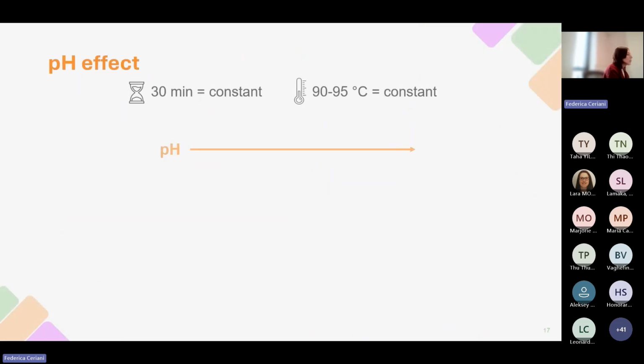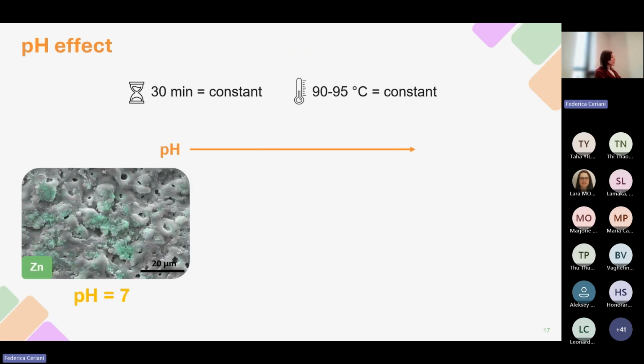To evaluate the pH effect on the sealing post-treatment, different tests are carried out, keeping constant the treatment time, equal to 30 minutes, and the treatment temperature, 90-95 Celsius degree, while the pH is changed. In the first case, an initial bath solution pH equal to 7 is tested.